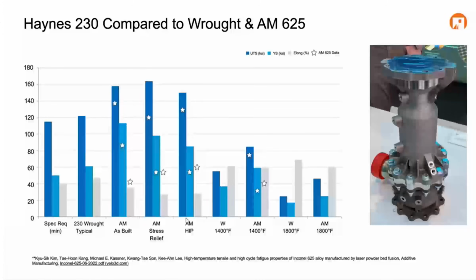The reason we see a little bit of property degradation from the stress relief is we get a bit of relaxation of residual stresses—these were taken in the Z direction—which can reduce your yield strength slightly, but the ultimate tensile strength slightly increases because we're getting a higher fraction of those tungsten carbides precipitating out. During the hipping process, the combination of high temperature and high pressure causes it to start to recrystallize, so the benefit of the reduced grain size starts to go away, and we see a slight degradation in properties but a slight uptick in elongation.